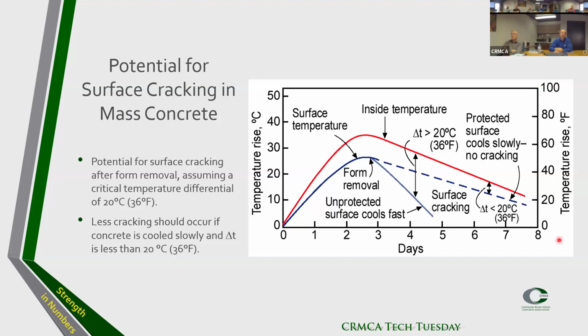That's just something to consider. And there are some really nice temperature sensors nowadays that you can place inside the concrete and on the outside that show you the temperature, like maturity meters, and that gives you a good indication when you can remove the form before you get into issues of potential cracking, surface cracking.